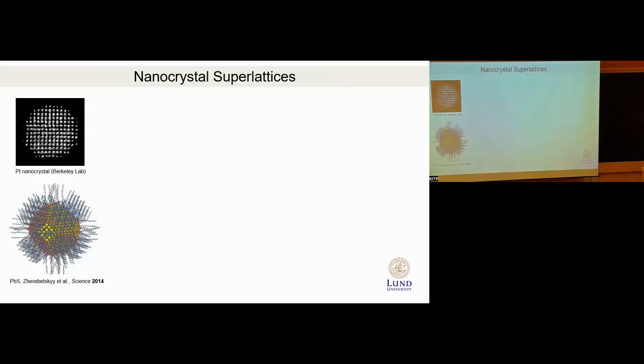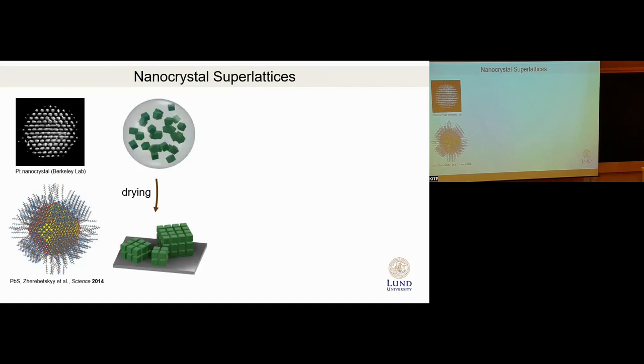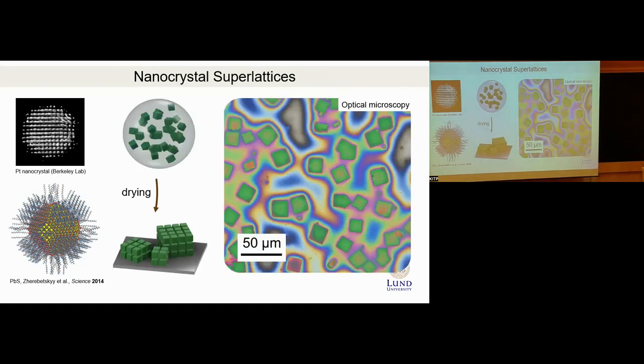So now, from nanocrystals to superlattices. Nanocrystals are crystals made of atoms, and we now look at nanocrystals as artificial atoms in the sense that we can build crystals out of them. For example, by solvent evaporation, from uniform nanocubes, one can form these microscopic, also square-shaped, superlattices. Each of these squares is assembled from nanocubes of about 10 nanometers.